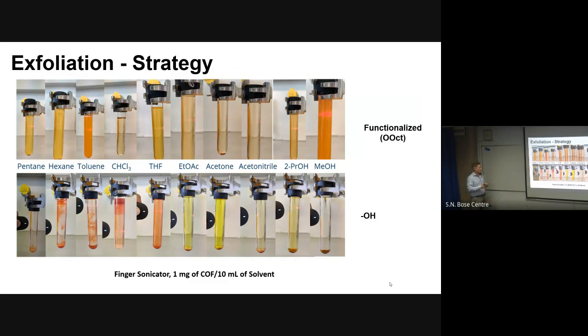So for the exfoliation, we did some first screening. We dispersed our material inside different solvents. Here, as an example, is the octyloxy functionalized material, the hydroxy functionalized material. We sonicated them for roughly 1 hour in these different solvents, then let them settle overnight, and took a look at the resulting solution. One very nice finding was that if we have the side chains on there, most of the solutions are quite stable. Of course, you see some precipitation, but after 24 hours you see nice Tyndall scattering, the materials are orange in color, and they stay in solution very long. If you don't have the side chains, there is much more precipitate, and in some cases there's barely any color left in the solution.